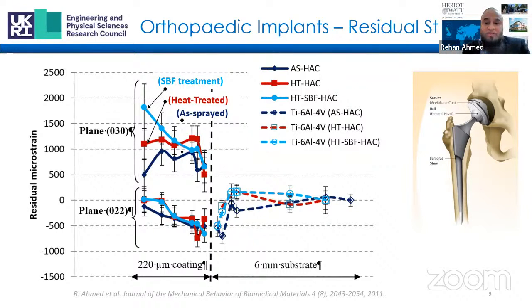So the slide shown here shows the through thickness microstrain measurement in the hydroxyapatite coatings in the as-sprayed, heat treated, and subjected to simulated body fluid conditions. And the term through thickness here is important because you need to understand the profile of residual stress near the surface, at the coating substrate interface, and within the substrate itself. And this particular measurement shows the analysis based on two different crystallographic planes, 030 and 022. The measured strain is significantly different in these two planes, and these differences highlight the importance of measuring residual stress across different orientations and using averaging or Rietveld refinement or some other techniques to comprehend the overall residual stress profile in these coatings.